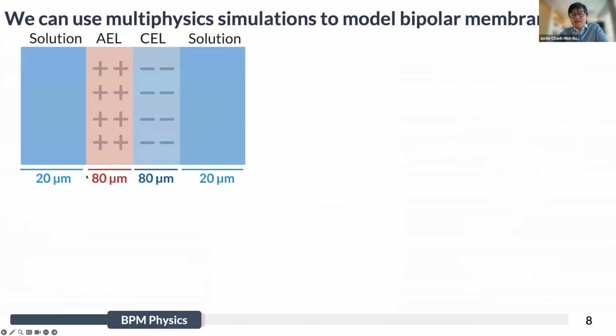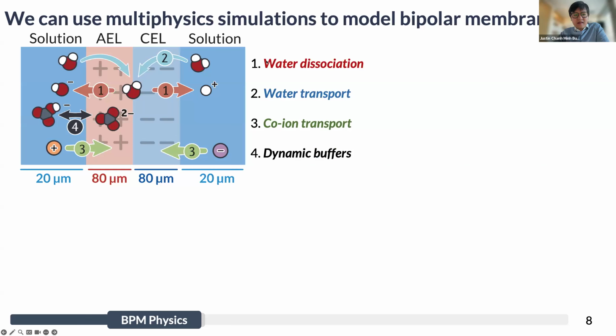And so the beauty of bipolar membranes is, there are these really nice mesoscale systems where you have two membranes inside of a bulk solution. And there are all of these different phenomena that occur within these materials. You have the dissociation of water at the interface, the transport of water from the bulk electrolyte to the interface for dissociation. You have the transport of different ions that can go in and out of the membranes. And then also you have dynamic buffering reactions. So for instance, the conversions of bicarbonate to carbonate to CO2, all of that is happening out of equilibrium and dynamically within the polymer during any of these processes. So we need to find a way to basically understand how all of these processes interact within these systems.